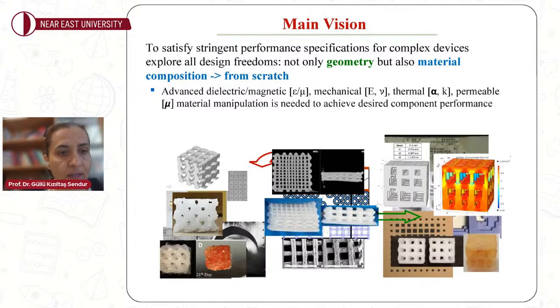We started doing that for electromagnetic applications, where we focused on the dielectric or magnetic properties, and were able to miniaturize the size of antennas and filters by 10-fold. We were able to fabricate antennas with different material compositions. And nowadays we adapt that to scaffolds that you see on top of the bottom picture, which was showing an electromagnetic device, where it's key to alter the scaffold's geometry as well as its material in such a way that effective regeneration takes place.